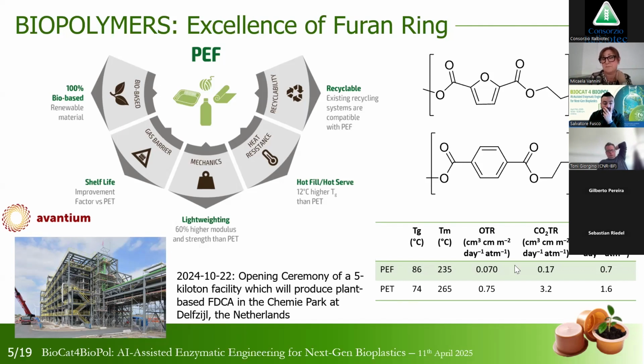You see here, for example, PEF has 5 times higher oxygen barrier than PET, 20 times higher CO2 barrier than PET, and 2 times higher water vapor barrier than PET.